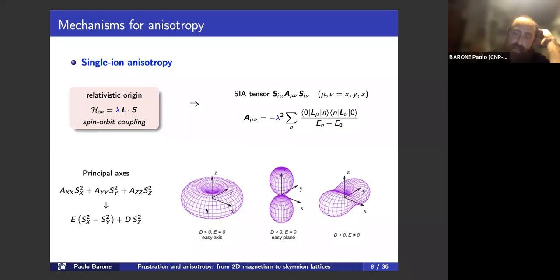And what I plot here are 3 simple examples of the potential surfaces that are induced by the single ion anisotropy. And of course, when we have a negative longitudinal component, the minimum of the energy is for spins aligned along the z direction. So this is an easy axis single ion anisotropy. In the opposite limit, we would have an easy plane where spins can freely rotate in the xy plane. So we still have a kind of continuous symmetry in this case. In the more general case, we have a more complex form of the potential surfaces where some specific directions show a saddle point in the potential surface.